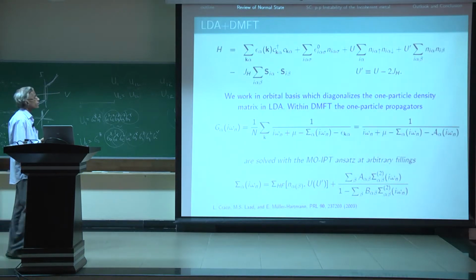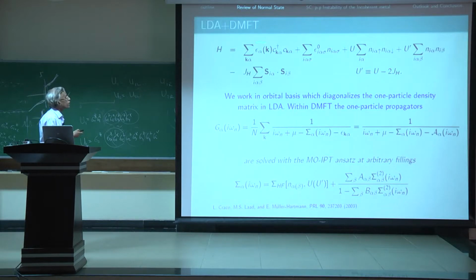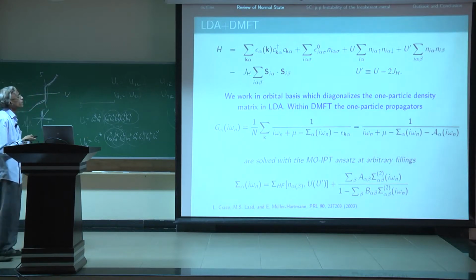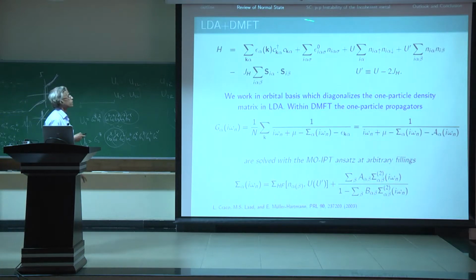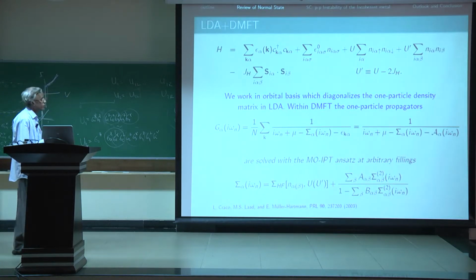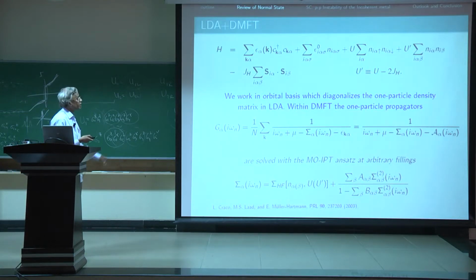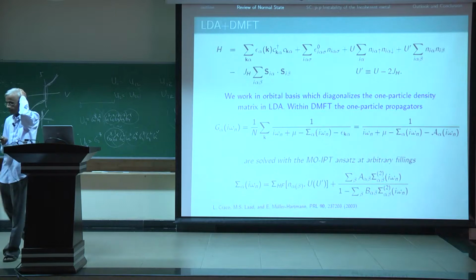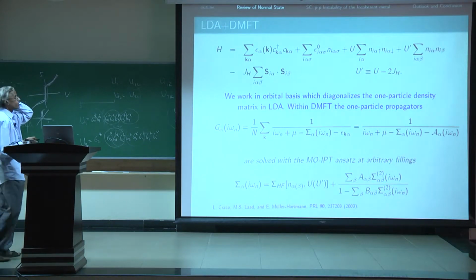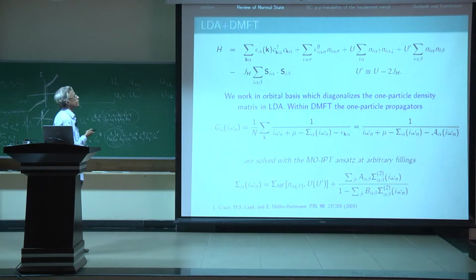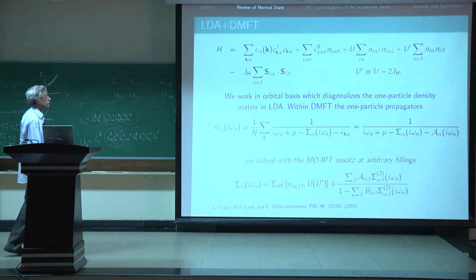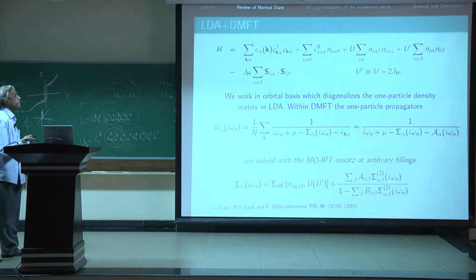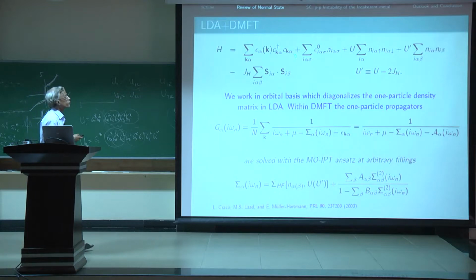Right. So basically, operationally, the starting point was to use DFT, the LMTO in our case, to compute the 3d bands in iron arsenides. And the idea behind neglecting the arsenic P states was that if you look at the LDA density of states, the weight of the arsenic P states is negligible or 0. Okay, so we restrict ourselves to 3d bands of iron, and I'll get to that in a minute.